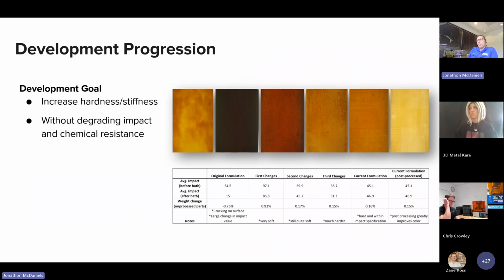The development progress was iterative. We would screen, test compatibility, formulate, find the limitations, and repeat. There were a lot of DOEs performed to fine tune. Each cycle, we would improve the properties of the material. You can see here it started off fairly soft and flexible, which is good for some applications, but it was not going to make a good mask. You need to have some stiffness, but you can't have brittleness. So we worked to increase the hardness and the stiffness without degrading the impact and the chemical resistance.